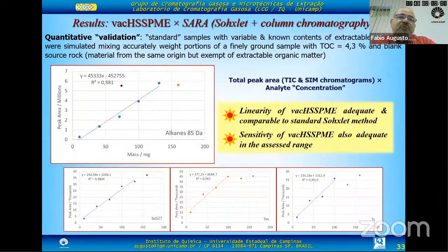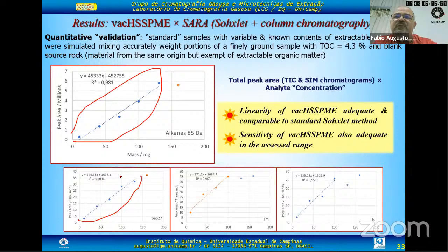As for the quantitative validation, we performed a sort of quantitative validation for this procedure. The problem is we don't have standard samples. We have no known amounts of each marker. So what we did, we selected a sample with some content of organic carbon, 4.3% of total organic carbon, mixed with rock exempt of extractable organic matter. We mixed known amounts of each rock and extracted to simulate rocks with different amounts of extractable oil. And it seems that vacuum headspace solid phase microextraction is indeed a quantitative approach. You can quantitate in a limited range the biomarkers in the rocks.